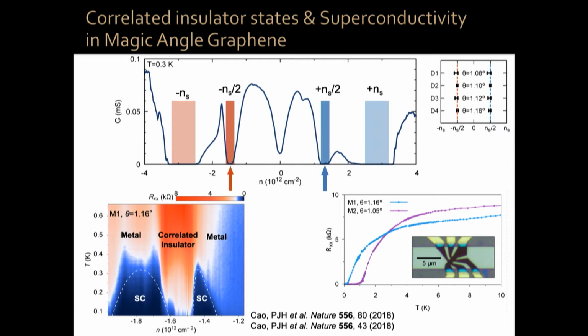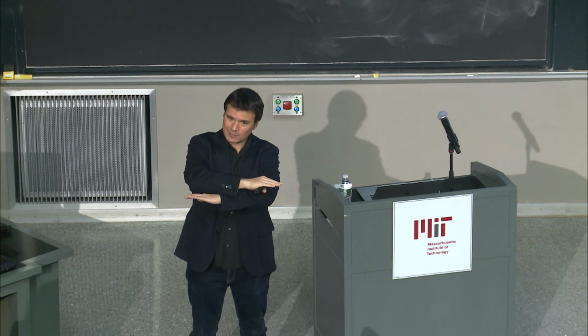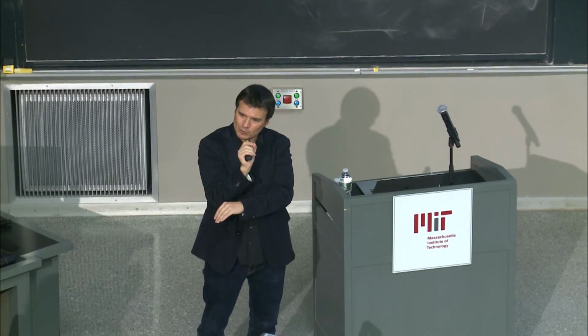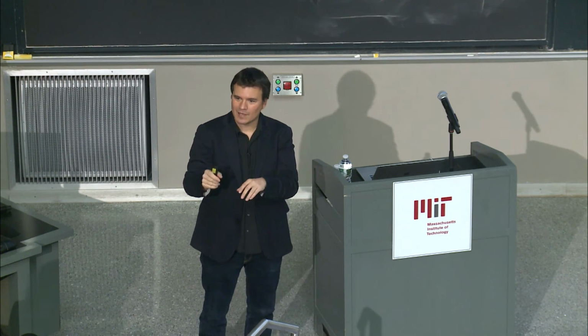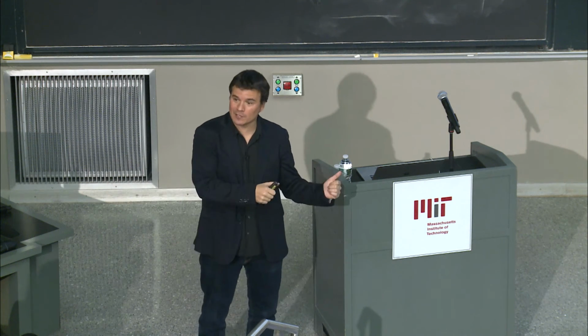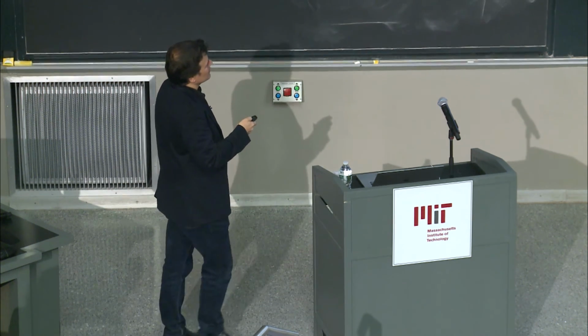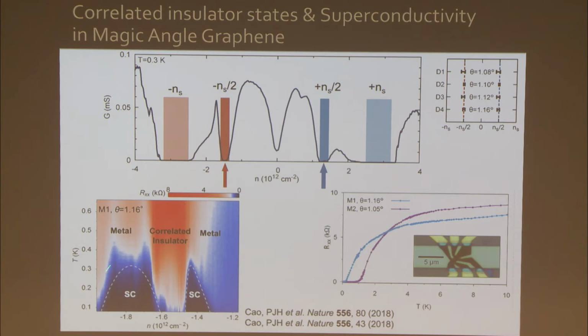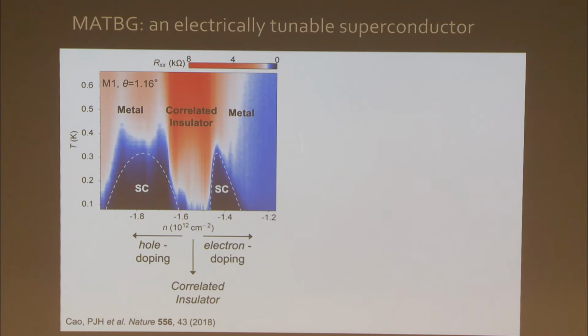That happens only, again, if your twist angle is very close to 1.1 degrees. But moreover, if you start now with that density and you have this insulator, now you add just a fraction, 0.1, 0.2 electrons per moire unit cell, and the system goes from insulator to superconductor, okay? And in fact, it is an electrically tunable superconductor where the critical temperature can be tuned by the amount of density of electrons that you put on it. Really tiny, minute amounts of electrons, you can go between insulators and superconductors, okay? So this, we published in 2018.